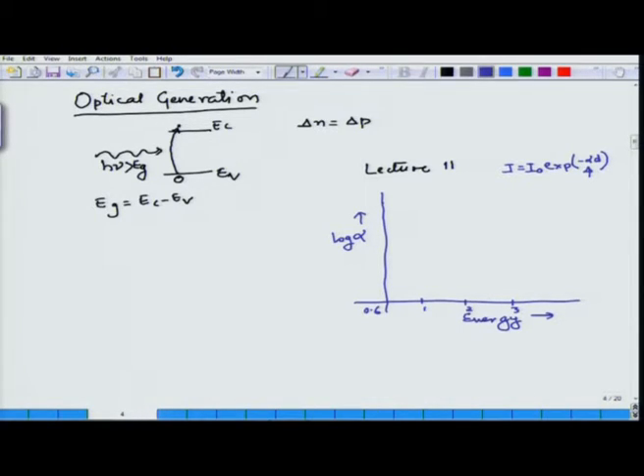So, if I have gallium arsenide, which has a band gap of close to around 1.4, it has an absorption coefficient which increases and then it plateaus, that is, absorption coefficient increases in this manner. On the other hand, if I have silicon, whose band gap is around 1.1, absorption coefficient is small initially, then at a certain value it increases rapidly and becomes similar to gallium arsenide. This is silicon, this is gallium arsenide. I can take one more example. Let me take germanium, which is around 0.67 band gap. The absorption coefficient increases a little in the beginning, and then again it also increases rapidly later, becoming saturated at values closer to gallium arsenide.